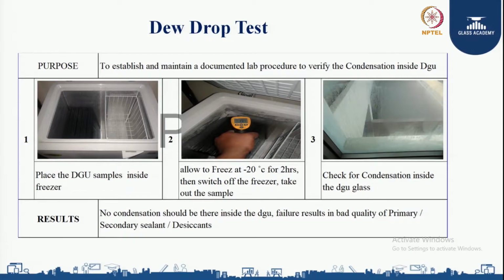Next is the dew drop test, which checks for condensation inside the DGU. We take a DGU sample and keep it inside a freezer at minus 18 degrees centigrade for around 2 to 3 hours, then take out the sample and check for condensation.